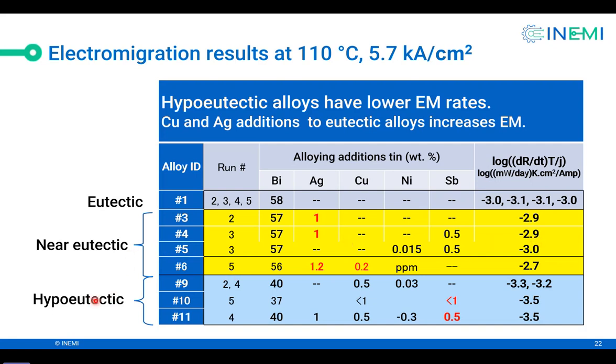Now, hypoeutectic, which has less bismuth, like 37 to 40%. Here, notice these values are -3.3, -3.2, -3.5. So this is slower electromigration. Hypoeutectic solder has electromigration at a slower rate. And antimony addition further decreases the electromigration rate. Without antimony, it was -3.2 and -3.3. With antimony, it went to -3.5, -3.5. So antimony decreases electromigration rate.